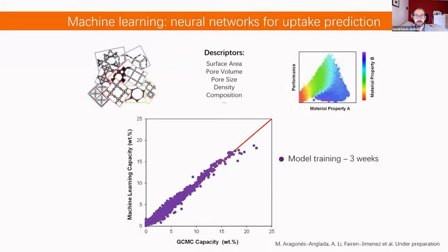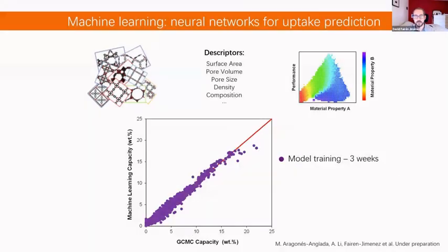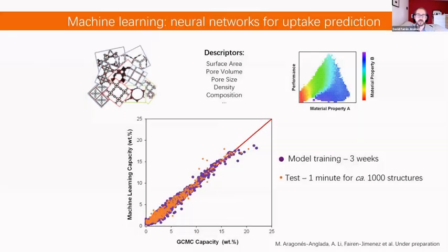This is the model training. This is something that took 3 weeks to obtain the Monte Carlo simulations for thousands of materials. And then in a question of 1 minute, we can test 1,000 structures. And you can see how close the Monte Carlo and the machine learning results are. They are really, really close. They work extremely well. Amazing results, really, really happy. And this is finally a deterministic prediction.